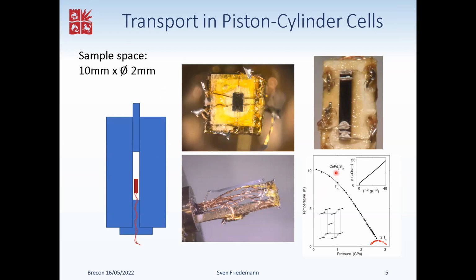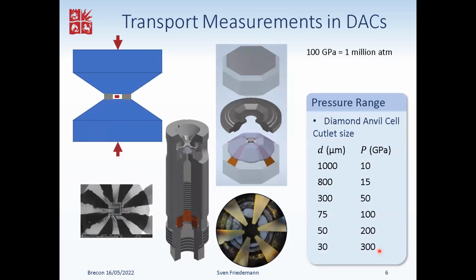So for instance, all the work on cerium palladium-2 silicon-2, which is the prototypical quantum critical superconductor, has all been done in piston cylinder cells. And there's a lot of reliability and a good success rate for piston cylinder cells. It's still fiddly because we're talking about sub-millimeter or millimeter size samples and getting all the wires and everything arranged, but there's a good success rate with that. Diamond anvil cells, it gets a bit more tricky.